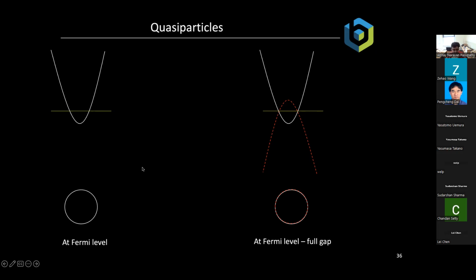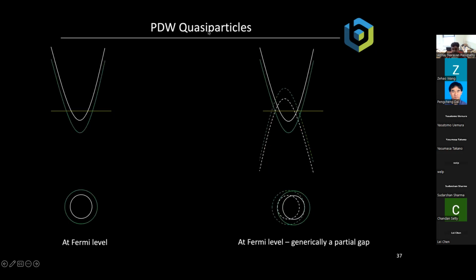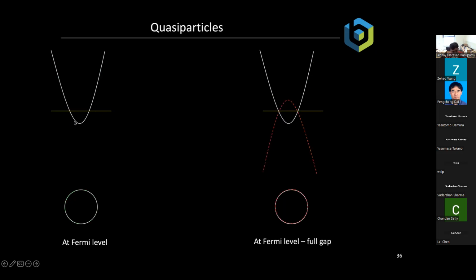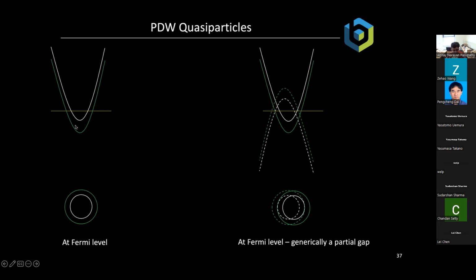We can try to do the same thing for the FFLO state. So here is the FFLO state, where, remember, there's a Zeeman effect. So there's a spin up and there's a spin down Fermi surface. That's the green one and the white one. And if I want to ask what the excitation spectrum of this particular superconductor is, now remember that the pairs are not formed between K and minus K.